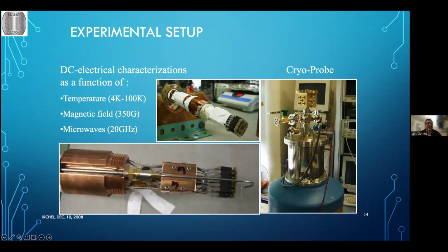In this case, the materials that I studied at this time were high temperature superconductors. Nothing like niobium. It was actually YBCO, or no, in this case it was lanthanum strontium copper oxide. The transition temperature for those materials is about 30 to 40 kelvins, depending upon the doping state of the superconductor.